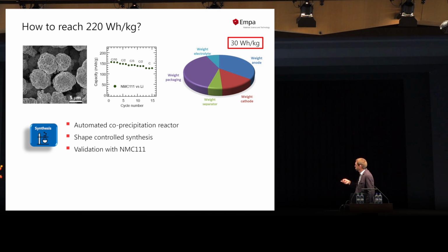This is the result here. We get out about 150 milliampere hours per gram of material. You can see this here as a function of cycle number, and the C rates here represent at what discharge rate and charge rate we are cycling the battery.